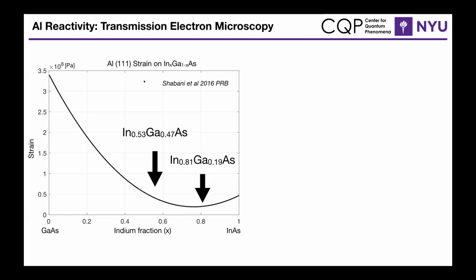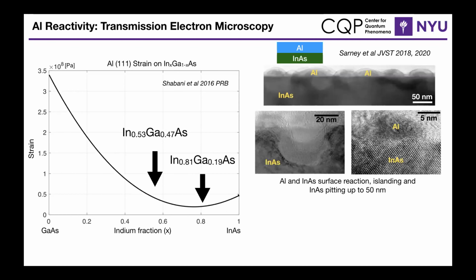So some of the problems of growing an aluminum layer strained to the underlying indium phosphide substrate can be summarized in this plot, which shows the strain energy as a function of the indium content or the composition. And you can see that there's a minimum of the strain energy on the aluminum layer near 0.8, but as you go away from 0.8, so near where you're lattice matched to indium phosphide, you actually have a strain energy which is near double of what it is at just InGaAs 0.8. And the same can be seen on the other end if you grow aluminum directly on indium arsenide.